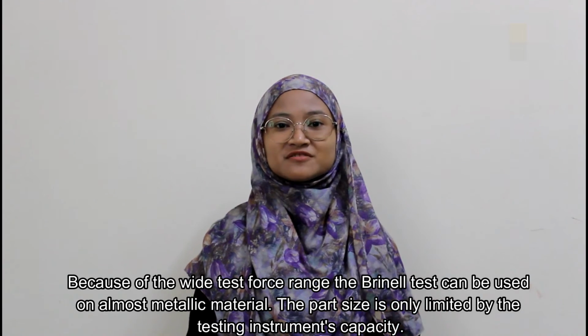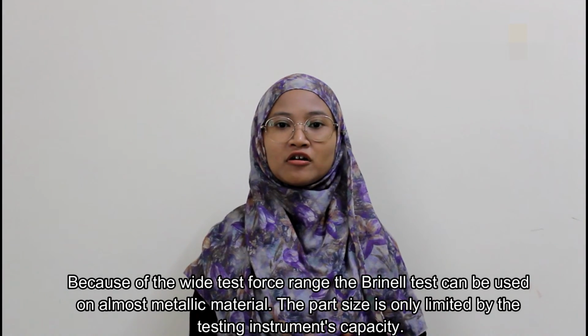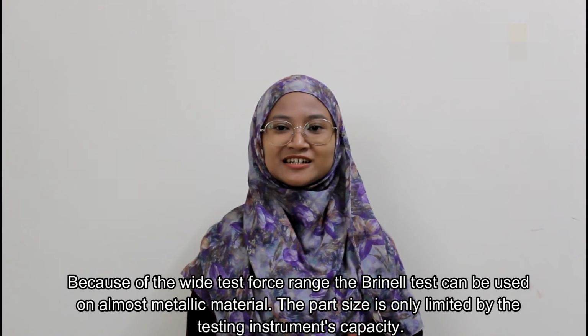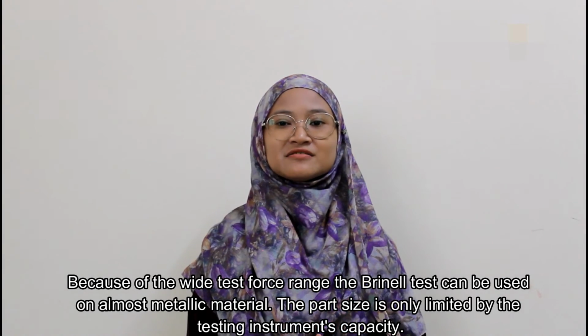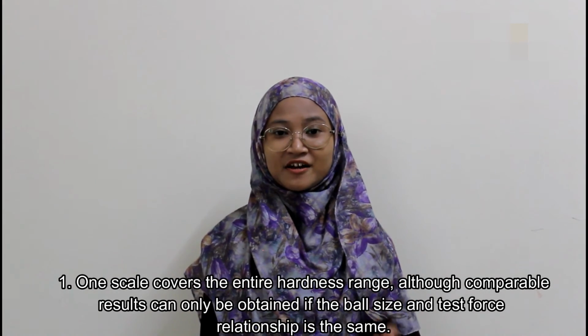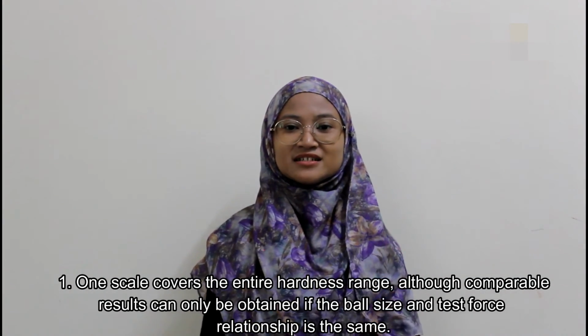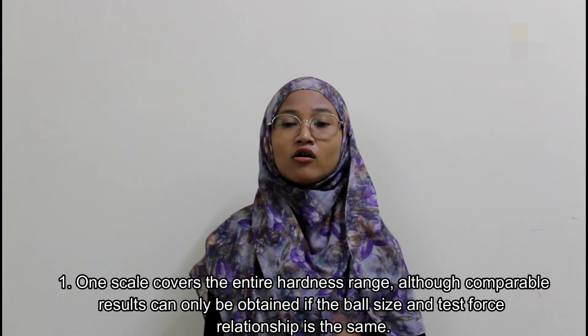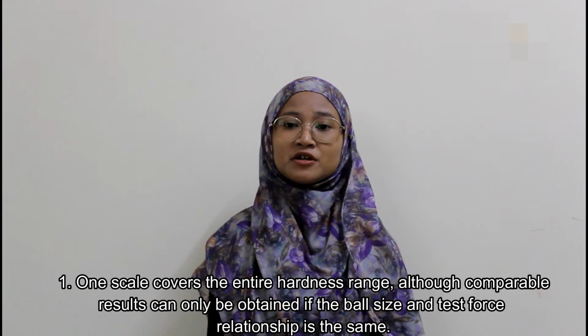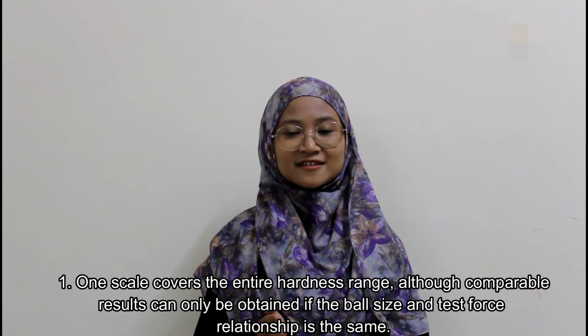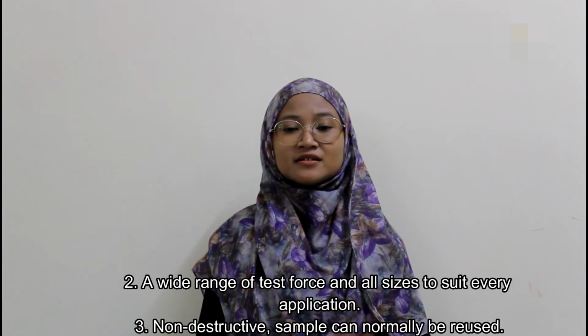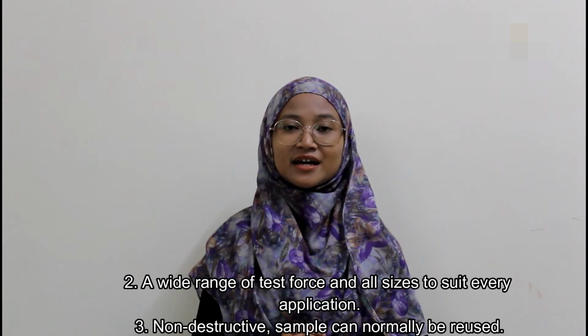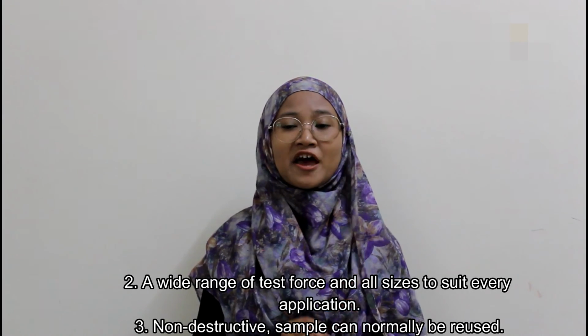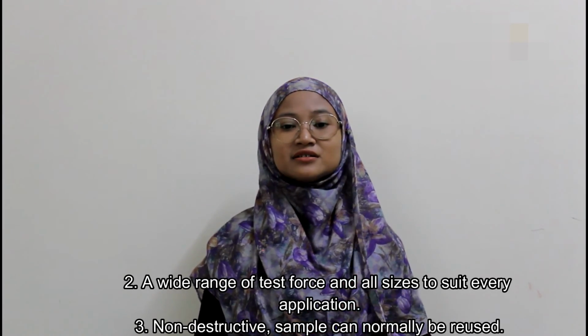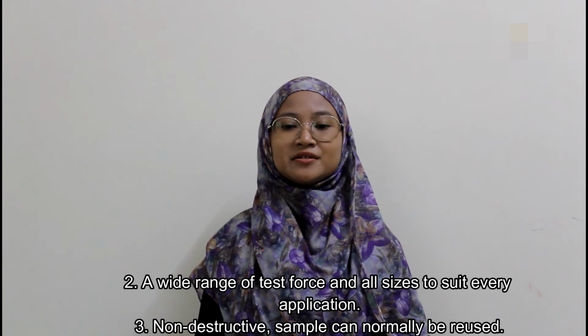The application of the Brinell test. Because of the wide test force range, the Brinell test can be used on almost any metallic material. The part size is only limited by the testing instrument's capacity. For the strengths, firstly, one scale covers the entire hardness range, although comparable results can only be obtained if the ball size and test force relationship is the same. Second, a wide range of test force and all sizes to suit every application. Third, non-destructive, the sample can normally be reused.